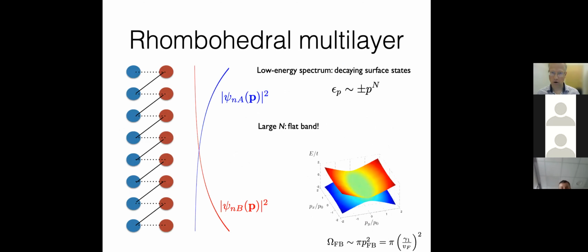Okay, if you look now at a rhombohedral multilayer, you can very easily make a model of this and study the spectrum. What you find is that it has a low energy spectrum with an approximate flat band. Basically, if you stack these layers, you notice that the top and bottom layer always have a single uncoupled lattice site. This site is uncoupled only at zero momentum. If you put a finite transverse momentum, there is a coupling, but this coupling will just delocalize the state up to a certain amount,